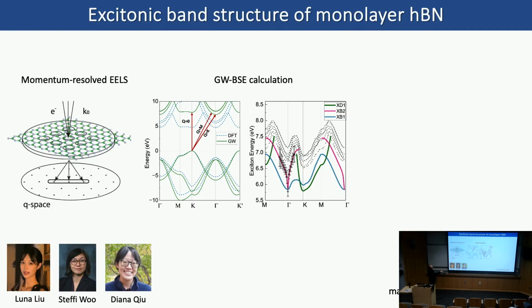And what's also interesting is that for this point, it's actually a dark excitonic band. So it's forbidden to jump from here to there, actually. So from theoretical calculation, we predict that hBN is an optically direct bandgap insulator. So only the gamma point is bright. There's a blue band, which we call exciton bright band number 1, and the pink band is called exciton band number 2. What's also interesting is that the pink band has a linear dispersion relation. So at this gamma point, you see that they form like a Dirac cone, which means in this case, the exciton doesn't have any mass. It's a massless exciton which acts like a photon.